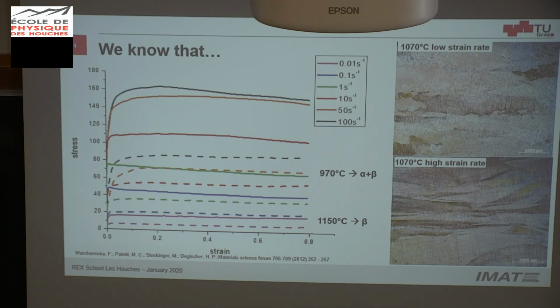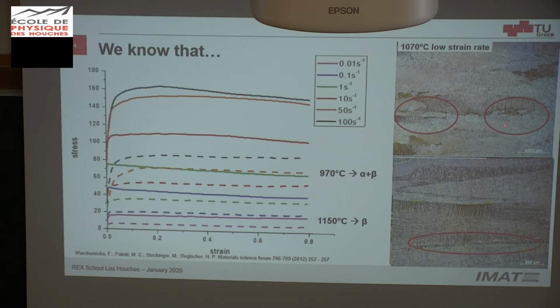So when you cool down, you have martensite. It's awful for reconstruction. So you see that there is no recrystallization. This is cooled down. There is no recrystallization, so the grain boundary is moved a bit. They are serrated with respect to strain rate, or with respect to the size of the subgrain actually. But there is no recrystallization.